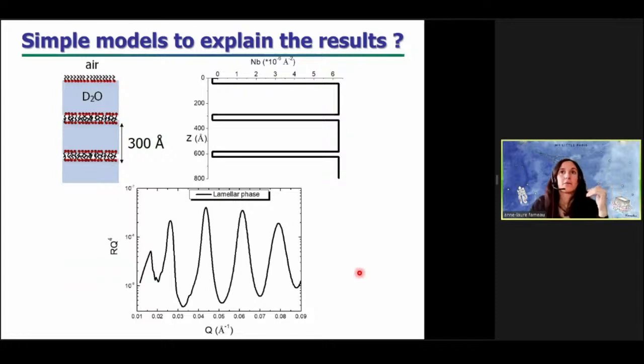So first, we wanted to see if these tubes are just unfolded at the interface and form lamellar phases with the distance between the lamellar phases of around 300 angstrom. So from this lamellar phase model at the interface, we calculated the profile of the fatty acid fraction according to the distance to the surface. And from this profile, we calculated the corresponding reflectivity curve that you can see here in black.